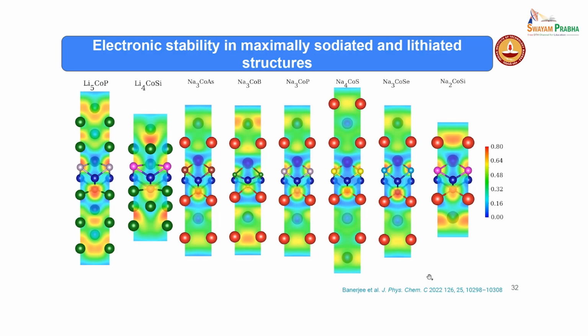Here there is a color coding also done, where a red color corresponds to a strong electron density between them, and a green color is close to what is called electron gas type. These are free electrons. If it is blue, this suggests that electron density is not at all there. You can clearly see that at the beginning, in the first layer, there is only ionic type interaction, but afterwards there are free electron gas type interactions between the atoms, that is helping to load more atoms in the cases of lithium and sodium.